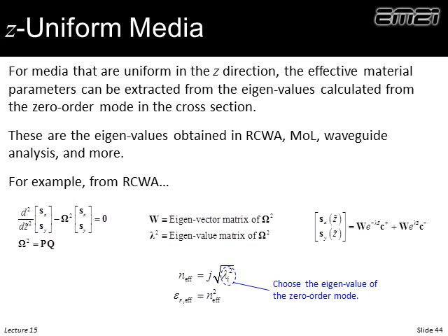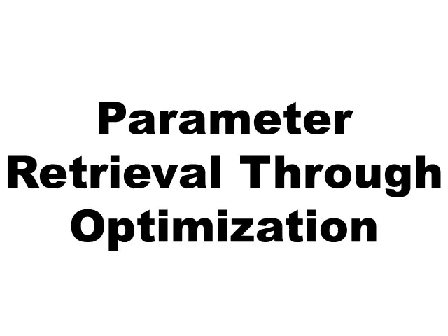If we're shallower than, let's say, a quarter wavelength, remember from our discussion of sub-wavelength gratings, that's when there's some additional physics happening here. The percentage of power inside the grating becomes less significant, and we saw that the effective material properties deviated pretty sharply. So this is really good for estimating the effective material properties for deep gratings and long uniform media. Not so good for real shallow. This is a pretty quick section.